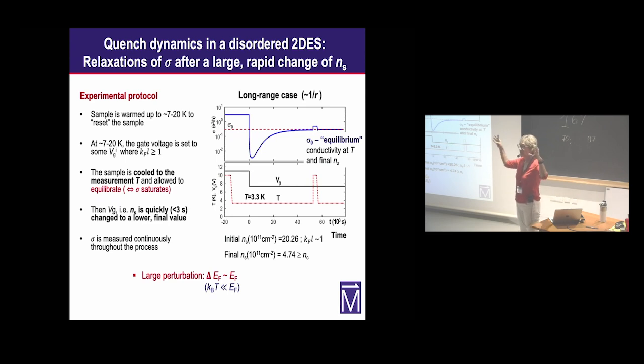What we do is start from high temperature, high density, where nothing interesting happens. We cool the system down to the measurement temperature. Then after some time, it doesn't matter how long we wait, we reduce the carrier density by a large amount. So we are taking the system very far from equilibrium. This is time equals 0, and then we follow the evolution of conductivity with time.